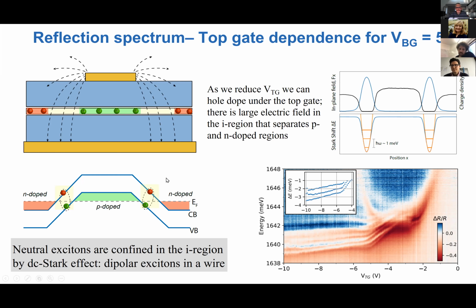And we can also think about, particularly in this gap region, having 1D excitons separated from a 1D channel of electrons. In that way, we can also think about probing the Luttinger liquid states using excitons that are in the immediate neighborhood. So the possibility seems to be very rich, but our focus now is on photon correlation. We want to see if indeed 1D enhances the interaction strongly enough that we could actually see anti-bunching in this system. This is very exotic. Thank you.